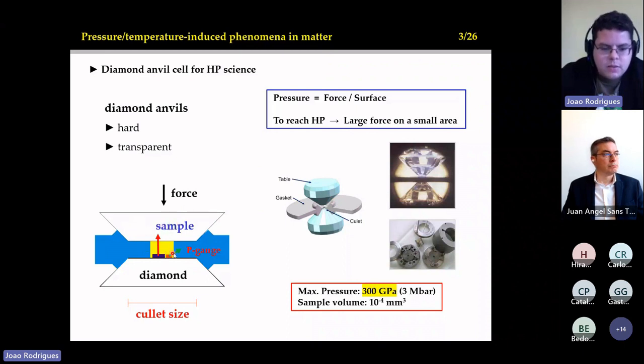We have the two diamonds, and in the middle we have a metal, which we call the gasket, and then there is a hole. In the middle of the hole, you can put your sample and your pressure gauge, which can be a material like gold or platinum, or also a luminescent material like ruby. Then, depending on the properties of the diamond, you can read different pressures. As we know, up to now, we can reach in the diamond anvil cell 300 GPa, or 3 megabars, in pressure. So it basically says that if you need to increase your pressure, you need to reduce your sample. This is the main point.